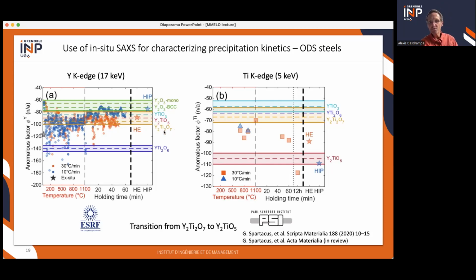So now if you want to discriminate between these two phases, you need to act on titanium because they have a factor of 2 in titanium. And so we did some experiments also at the titanium edge, which is more difficult because it's at lower energies. So you need an even thinner sample. And we did that. The first experiments were done at the ESRF, the second ones at PSI in Switzerland. And here, the two precipitates are well discriminated. And you can see that you have a kind of evolution. It was not in situ, it was ex situ, but still, you have a kind of evolution from one phase to another during the heat treatment. So it tells you the transition between two phases that is very difficult to observe by other ways.